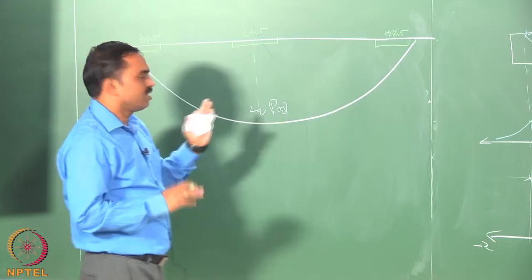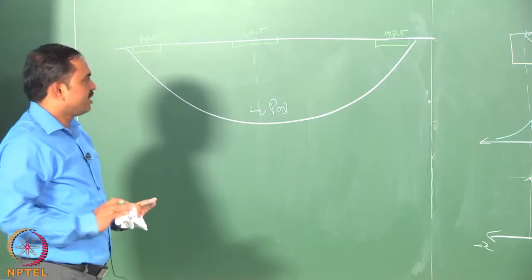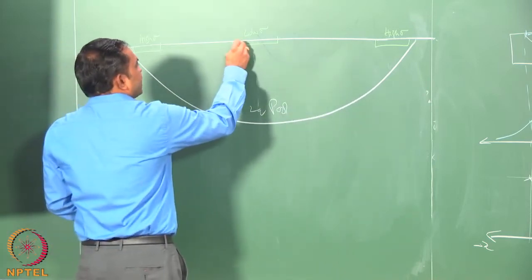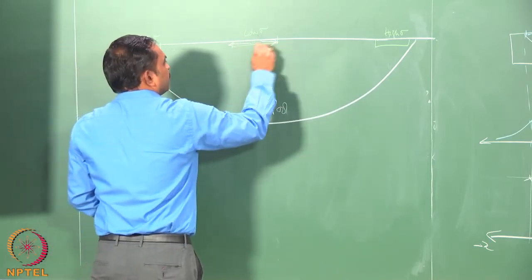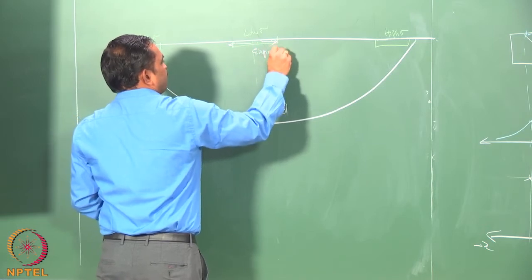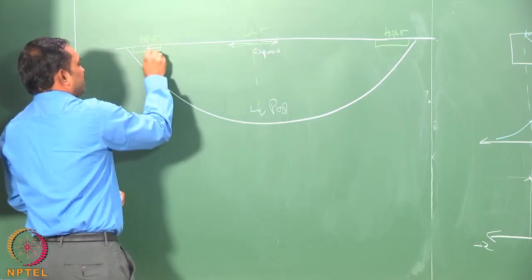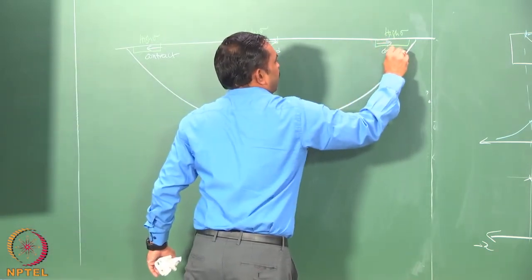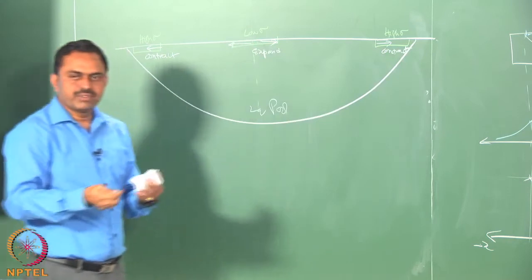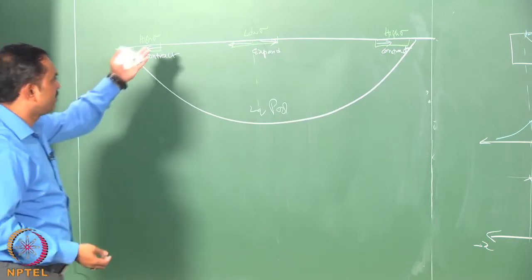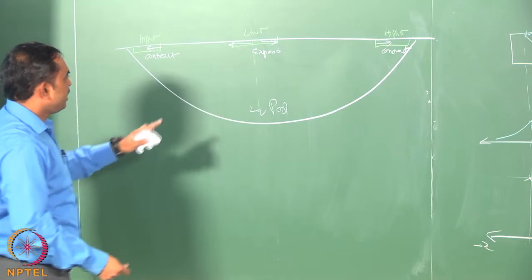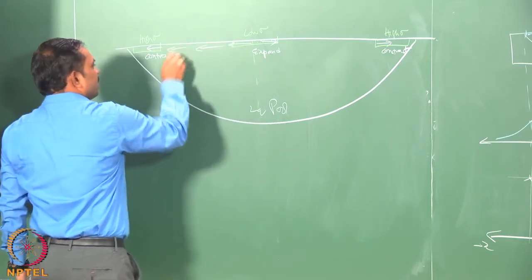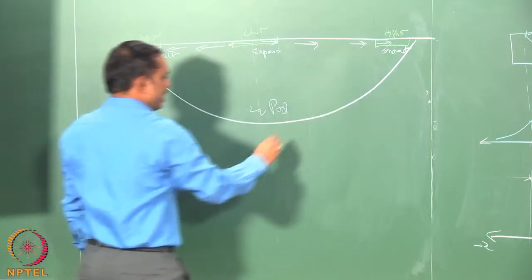Both ways the multiplication of surface tension with area can be minimized, which means that the way this should move is that if this layer can expand, and if this can contract, then you achieve the surface tension contribution to the energy of the surface coming down, and this means that the direction of the flow is such that it goes like that, radially outward.